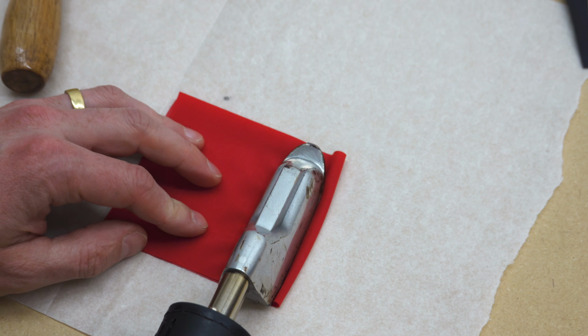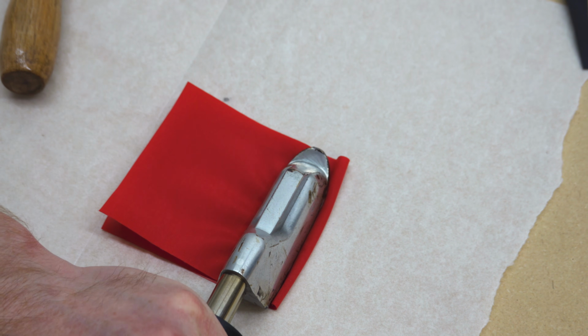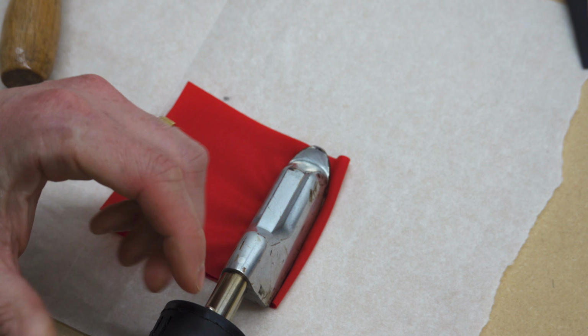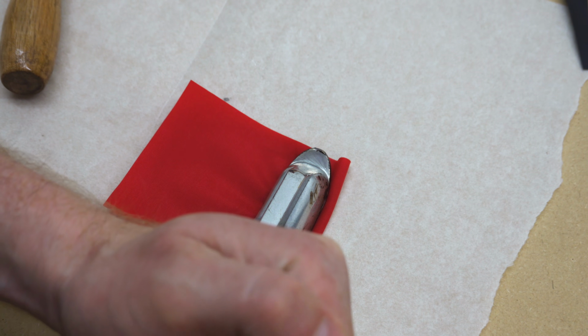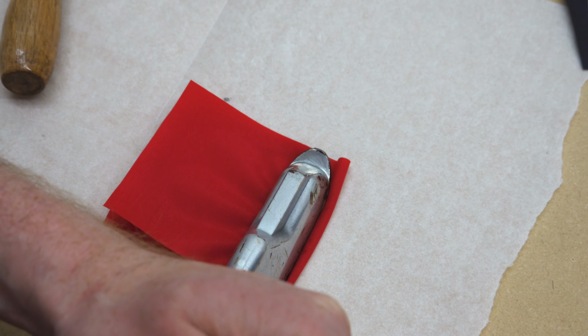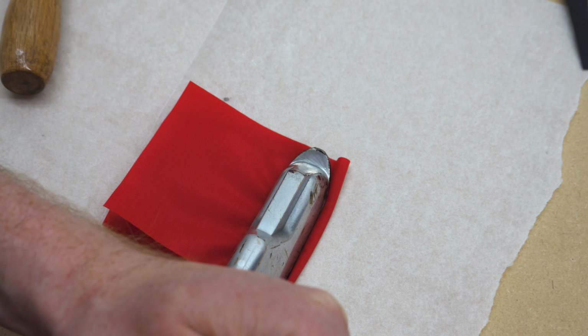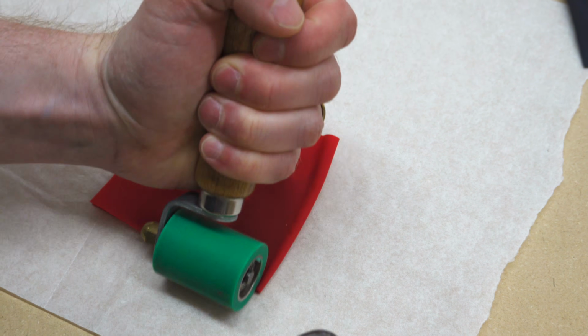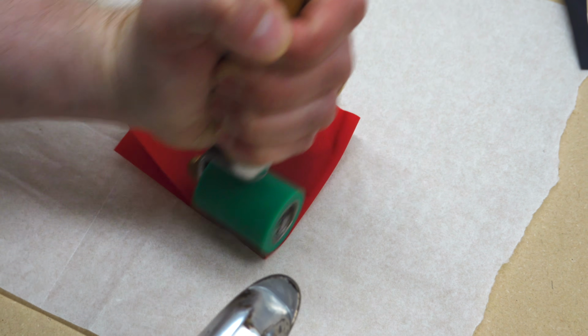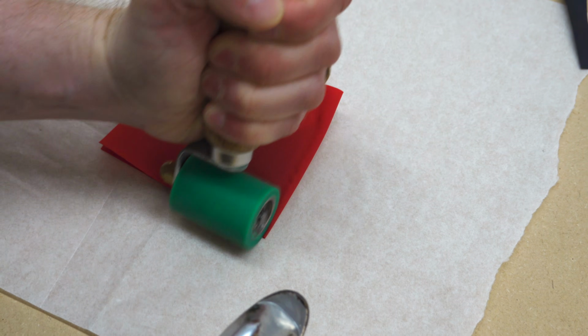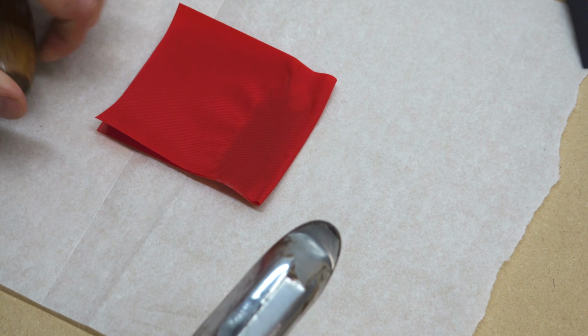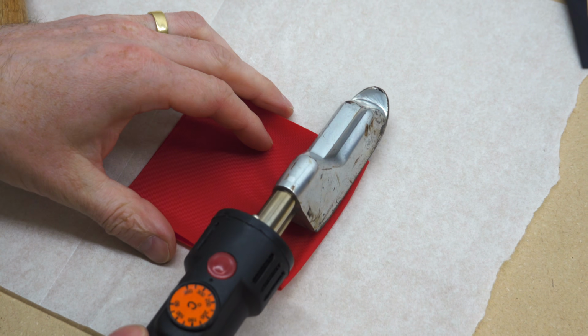None of my irons will get so hot as to be completely unusable, but as the temperature increases above the optimal range, you'll notice that the fabric tends to wrinkle and shrink more noticeably when the iron is applied, and the TPU will fully liquefy instead of just partially melting, which you can notice because the fabric tends to slide sideways more easily when you apply any sideways pressure.